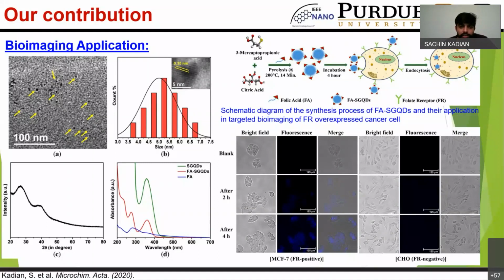So I would suggest going for a very dilute solution, and then you can find your real size. But for the true size, I would suggest going for TEM. DLS can give you the estimated size, but it would not be the true one.